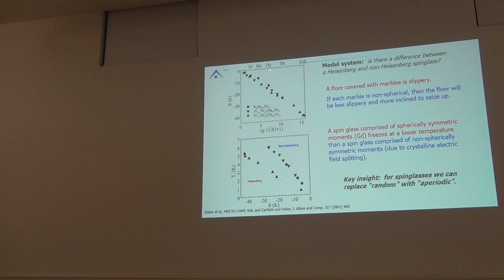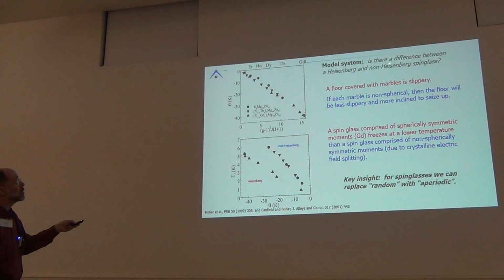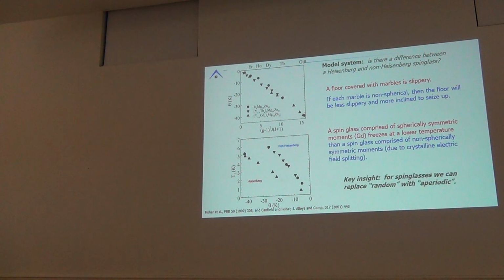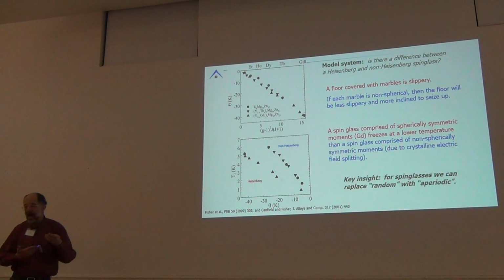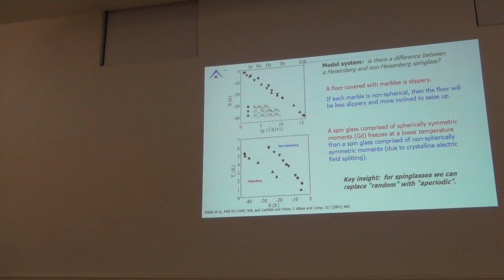So one of the questions we wanted to ask is there a difference between a Heisenberg and non-Heisenberg spin glass? The reason I pick on Heisenberg is gadolinium has no crystal electric field splitting. It has no local moment anisotropy. It's a perfect Heisenberg moment. The other rare earths will be non-Heisenberg. So I can look at the paramagnetic Curie-Weiss theta as a function of de Gennes scaling for all of these materials, the pure as well as an yttrium-terbium dilution and yttrium-gadolinium dilution. They all follow de Gennes scaling, which tells me the magnetic interactions are trivial.